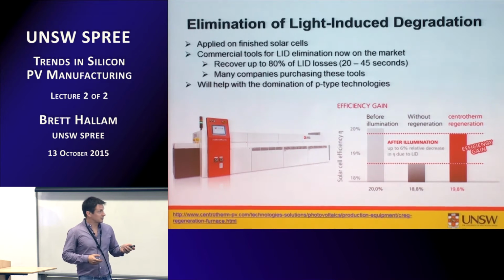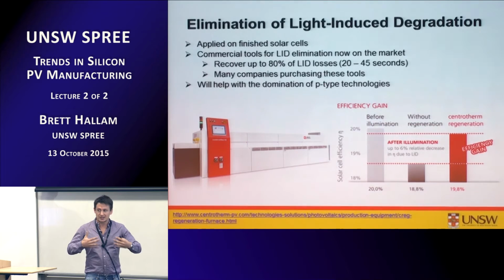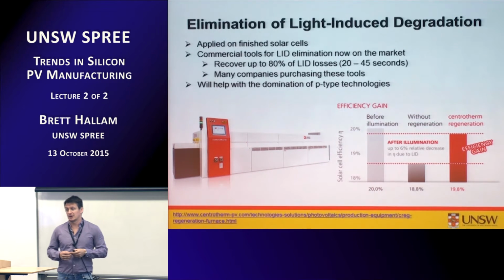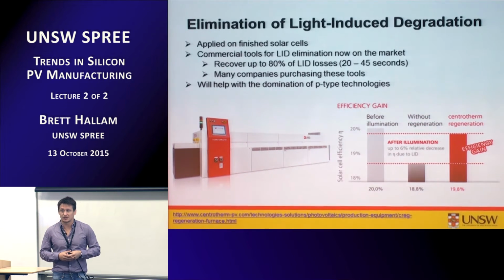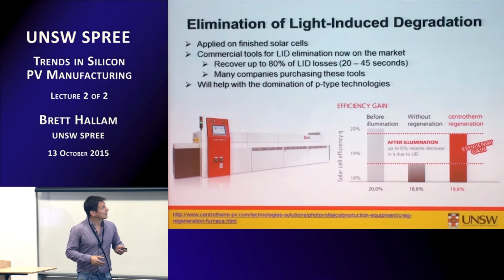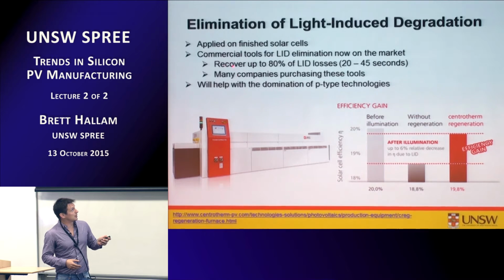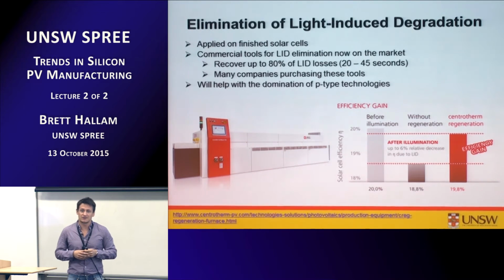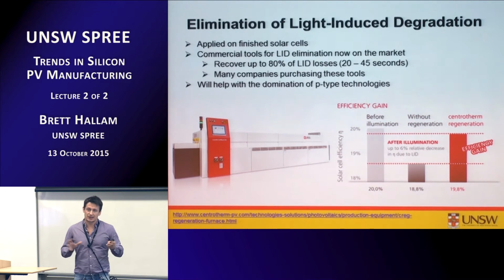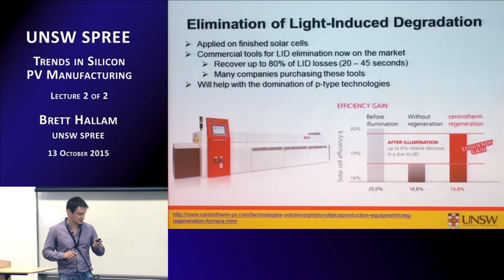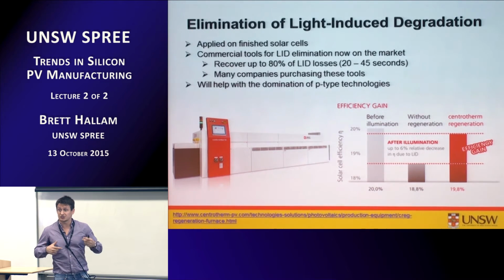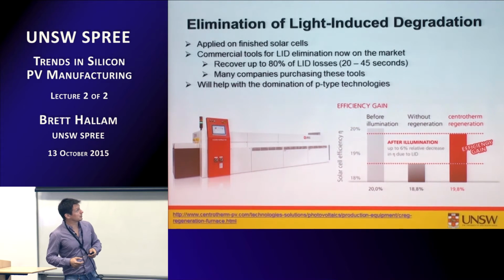And so with these kind of processes, P-type again becomes more appealing, because a lot of the reason in going for N-type technologies is the avoidance of the boron-oxygen defect. So this tool is quoted as being able to recover about 80% of the efficiency losses due to LID, taking about 20 to 45 seconds, but it does depend on the solar cell architecture, the lifetime in the silicon, and I'll go over a little bit of that shortly.